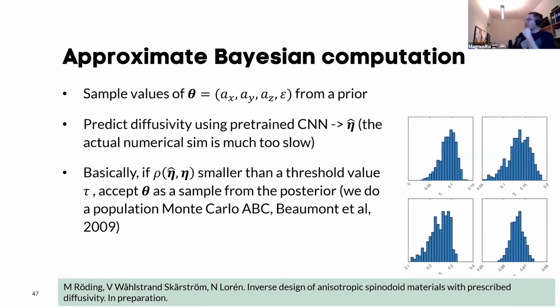And we use something which is called approximate Bayesian computation, which I'm not going to talk so much about, but basically we can sample values from this vector of the generation parameters. We can generate virtual microstructures from that model. We can predict the diffusivity in all 3 directions using a CNN that we have trained specifically for this task, which is way, way, way faster than doing the actual numerical simulation, like many orders of magnitude faster. And we accept this structure as a part of the posterior if the difference between the prescribed property eta and the predicted property of the simulated structure eta hat is not too large.